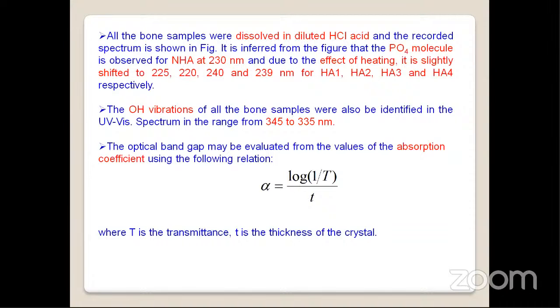And then we have a vibration. That is a molecular vibration of a PO4 molecule at 230, and due to the effect of heating, it is slightly shifted to some other points. The OH vibration is at 340 nanometers. The vibrations are present nearly in the range of 340 to 330. It is giving the OH vibration, which is due to the water molecules, and the other vibrations in the range from 220 to 240 are due to the PO4 molecules.